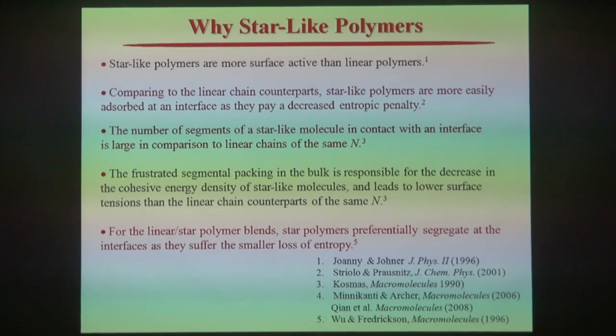Now if you are a polymer physicist, you know star-like polymers possess many intriguing physical properties for fundamental research. For example, compared with the linear chain counterpart, star-like polymers are more easily adsorbed at the interface as they pay a decreased entropic penalty because of the presence of multi-arms. The number of segments of star-like polymers in contact with an interface is large in comparison to the linear chain of similar molecular weight, again because of multi-arms. If you work on polymer blends composed of linear and star-like chains, you will see star-like polymer would preferentially segregate at the interface, again as they pay a decreased entropic penalty.